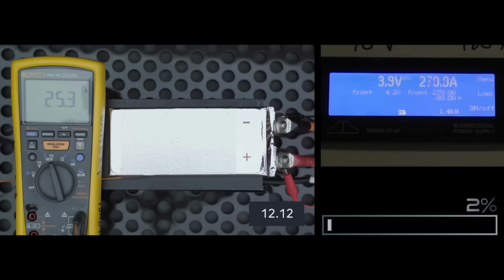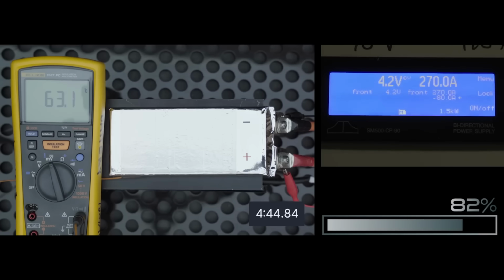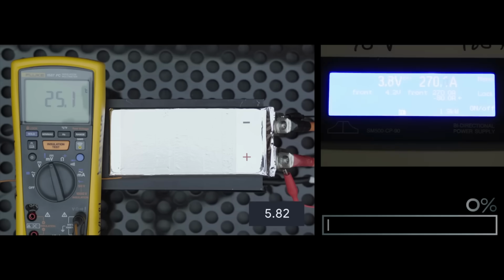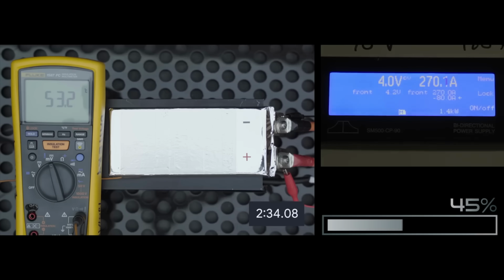The system is running at a constant voltage of 4.2 volts. However, the actual voltage gradually increases from 3.9 to 4.2 as the pack charges up. That's to be expected. Temperatures only increase from 25 Celsius to approximately 63.1 degrees Celsius after charging from 0 to 82% in 4 minutes and 44 seconds, despite charging at over 10 C. Like I mentioned, there's questions that you're going to have and I'm going to have, and maybe one day we'll meet them on site and answer these, but is there thermal management involved? Is that black plate that the cell is sitting on a cooling tray? We don't know. At 63 degrees Celsius, it's well within the operational range of their claimed pack.